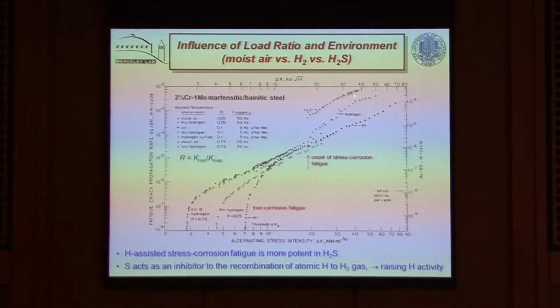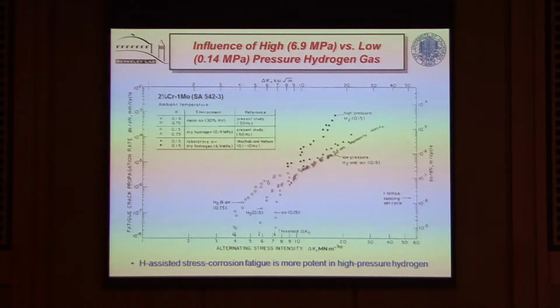This is in air. If we have hydrogen sulfide, of course, we get higher fugacities of hydrogen, and this leads to faster crack growth rates. This is in pressure. Now, this data was taken some time ago, and here we're dealing with the same superposition. This is basically air. Superposition in low-pressure hydrogen, which would be typically about a tenth of a megapascal. And at the time I looked at this, we had data at 7 megapascals. We got a much higher rate of crack growth in high-pressure hydrogen.